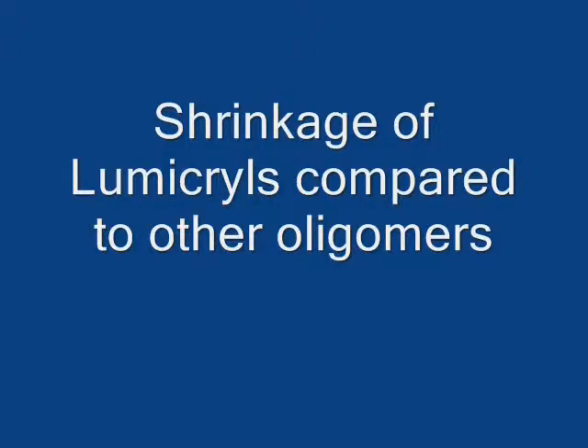The technology is acrylic, which has a number of intrinsic advantages, including an unsaturated backbone, good weathering, reasonable physical properties, and good adhesion. Being a higher molecular weight material, it is essentially covalently bonded prior to irradiation. That has several advantages. The first advantage is that there is less free space in the polymer matrix. And that free space, when you irradiate, gets taken up. The material actually has a dimensional change.